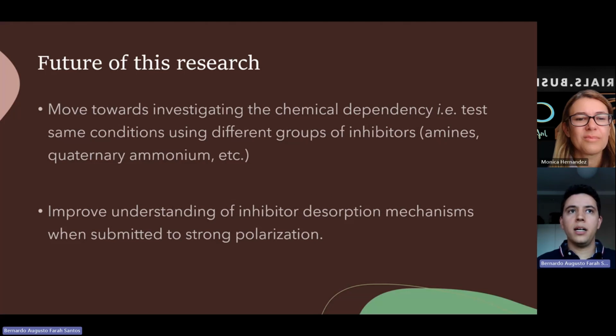And also, the second thing that I think is important is to improve the understanding that we have of the desorption mechanisms of the corrosion inhibitor, because like I said, at some point the current that flows on the surface of the working electrode of the carbon steel is too high and the inhibitor does not adsorb on the surface. But there is another situation that may happen.